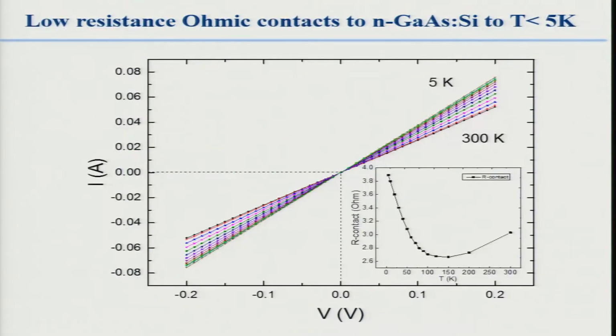So let me continue. Here's a plot of actually just measuring the resistance of the barrier and it's very low resistance, and it comes up a little bit at low temperatures due to localization effects, but it's still very low resistance, all the way down to 5 Kelvin. We've gone down to even lower resistance.